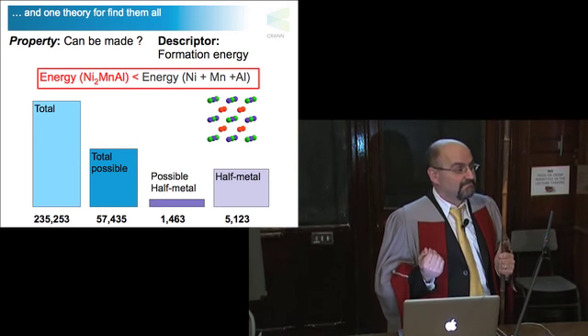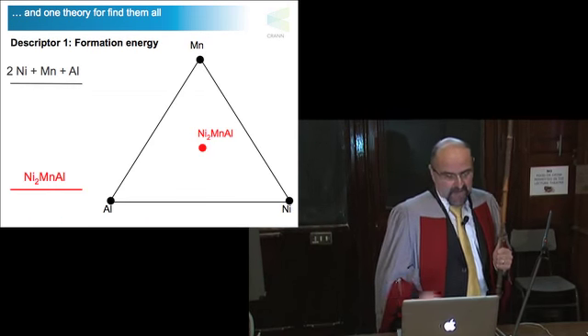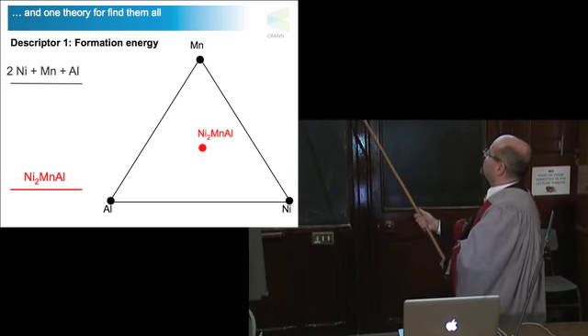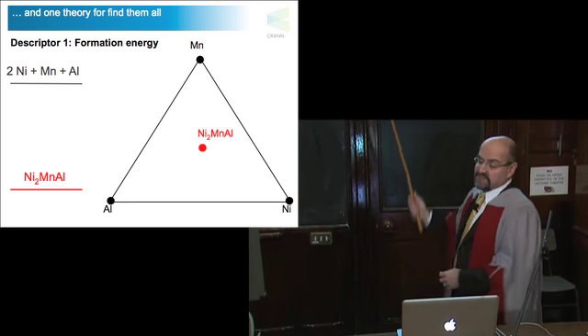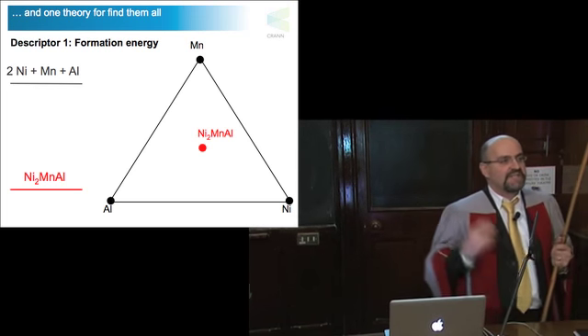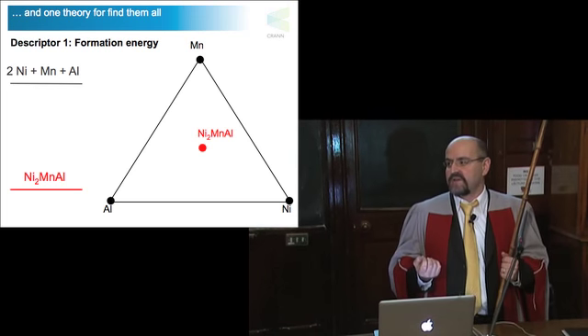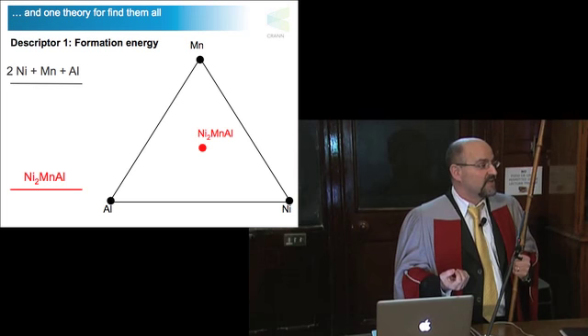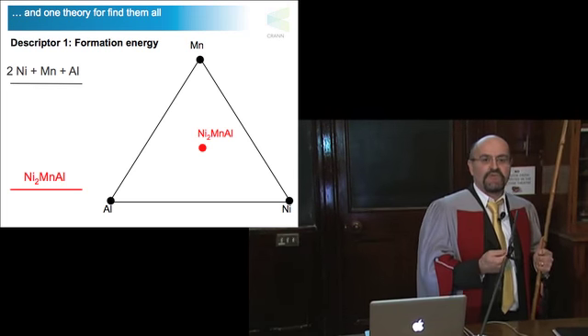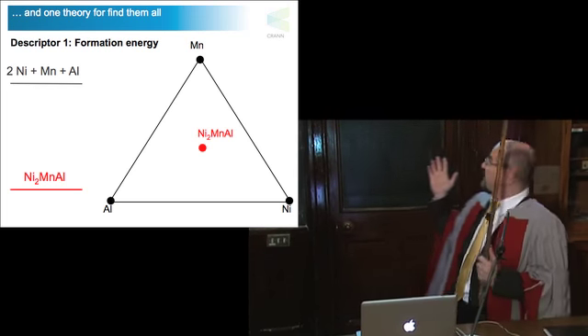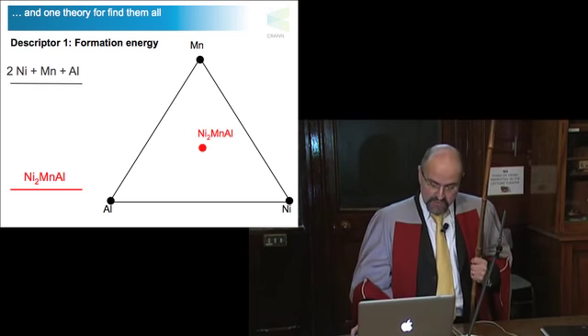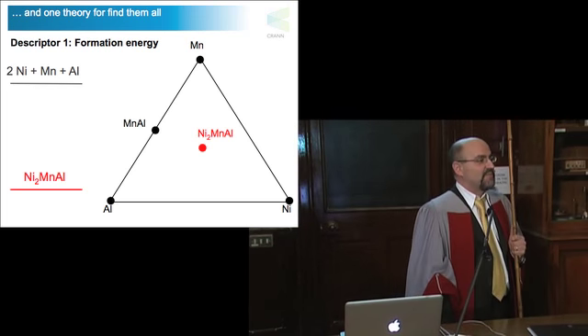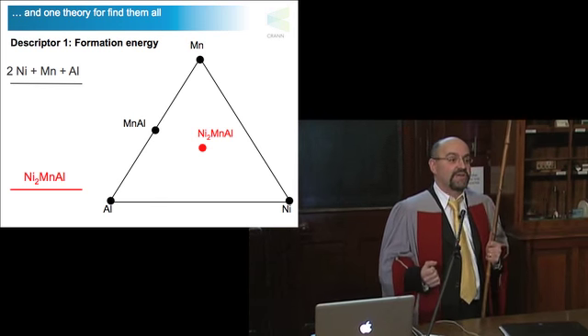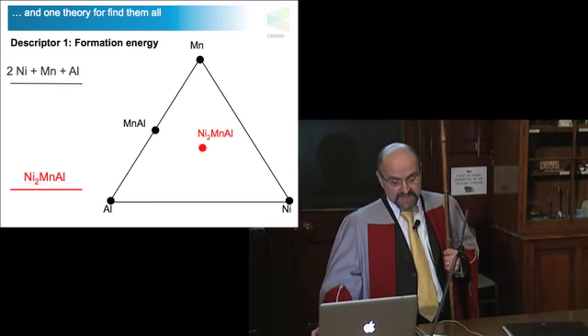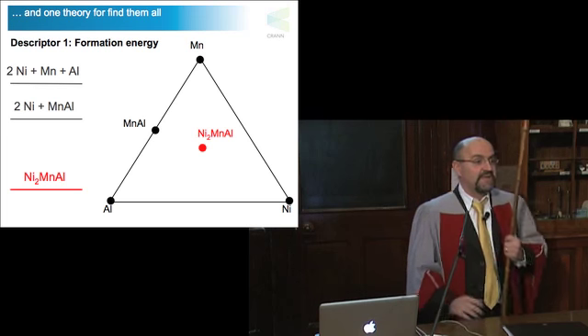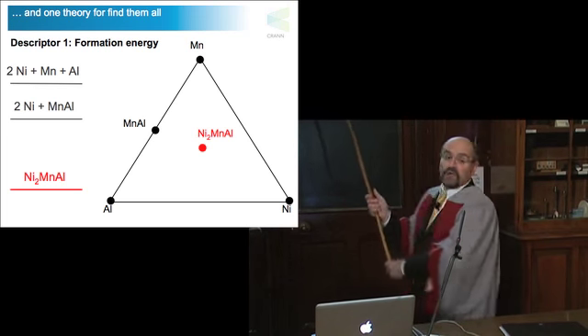But this is not the end, because once you find out that the energy of your new material is less than the energy of its parts, you have to ask, are these the only parts that can be made? And the answer, unfortunately, is no. So if you look in the other database of existing materials, for instance for this particular one, nickel, manganese, aluminum, you will find out that manganese aluminum can be made, and has been made for a long time. And this means that the material can also break into nickel plus this alloy.